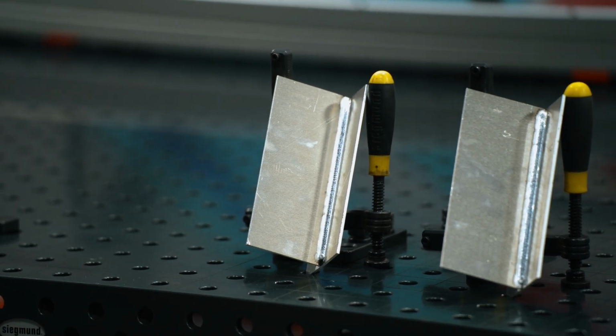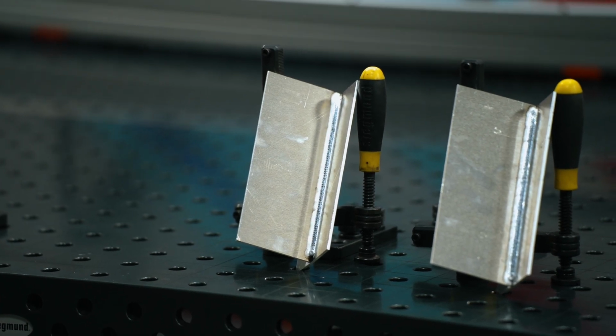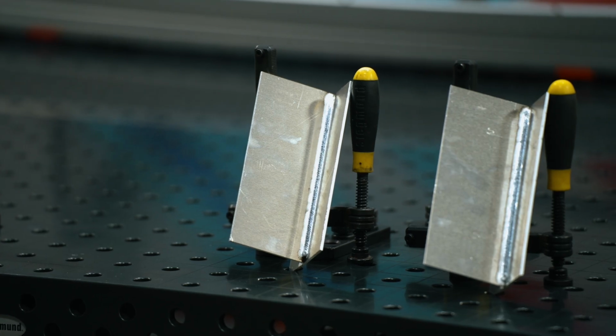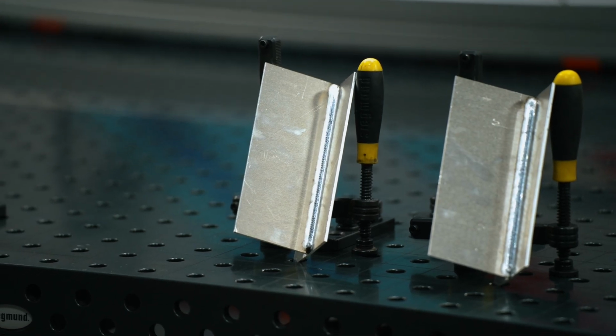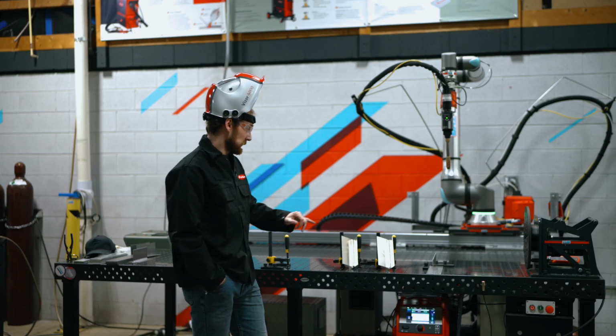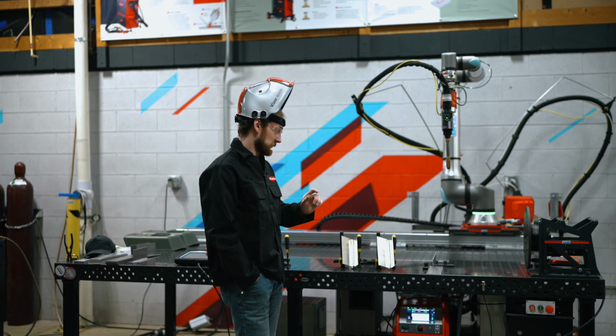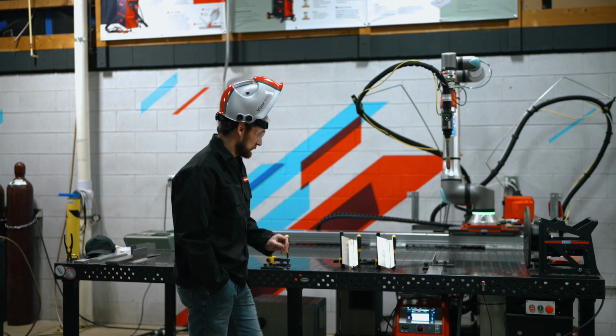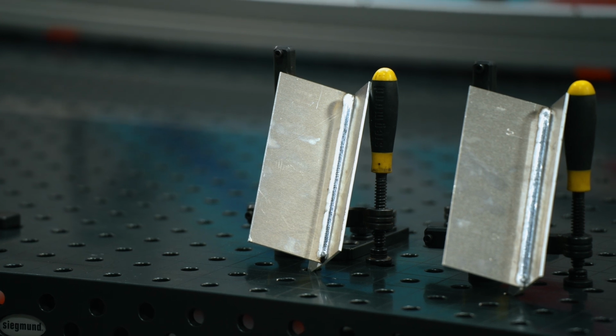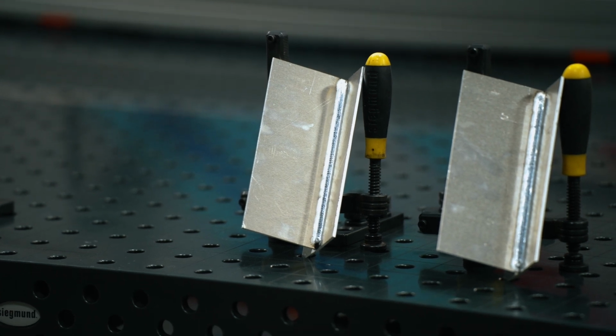On the second weld that we just did, we increased the low side correction of the CMT mix, allowing for the puddle to solidify and create a more stack dime appearance that's elongated versus the first, which was a shorter duration on the low side, and the stack of dimes is actually closer together.